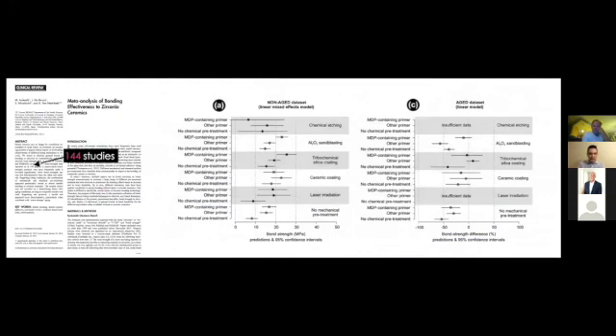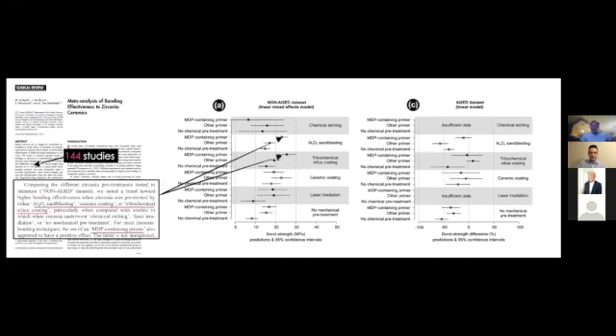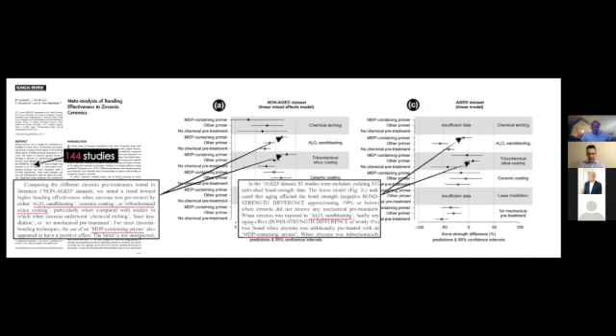I'm not going to go through all the data points, but this was a study in the Journal of Dental Research, the highest impact factor journal in dentistry. They looked at 144 different studies and compared a bunch of different factors. Broadly, they looked at laboratory data in which they tested bond strength immediately, and then some where they aged it. The conclusion was that if you sandblasted and applied that molecule MDP onto the surface of zirconia, you can improve its bond strength. So that showed that sandblasting and MDP allowed a bond to zirconia.